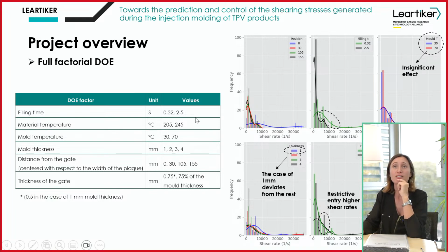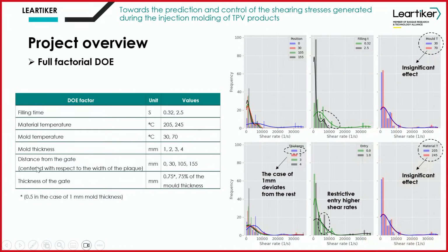So these are the values analyzed. We analyzed different filling times, different speeds, fast and slow injection molding, different material temperatures, mold thickness, as I said, from 1 to 4, different distances from the gate, and we also analyzed the thickness of the gate, so a more restrictive or non-restrictive gate. So as you can see in the histograms, we can see on the one hand that the mold temperature and material temperature have an insignificant effect. So these two variables have not much influence on the shear rate that is generated in the injection molding of these TPVs with different thicknesses.